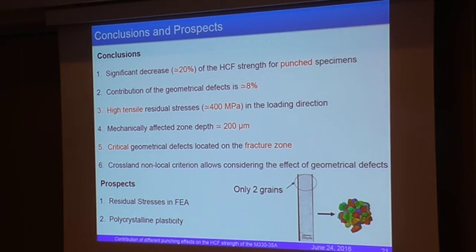Up to now, we didn't take into account the residual stresses in our finite element analysis, and well, that's another subject. That's not that easy to do. And since our grain size is about 100 microns and our sheets are 350 microns thick, we have between 2 and 3 grains along the thickness. So we assume that in order to get really representative results, we cannot do homogeneous simulation. So we will have to use crystal plasticity.